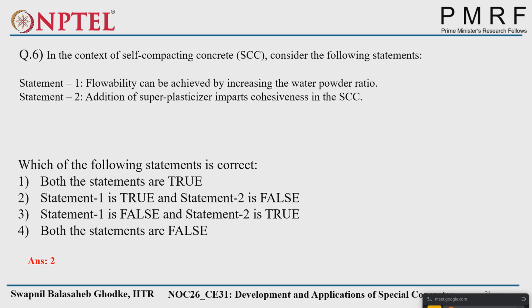Flowability can be achieved by increasing the water to powder ratio. Water increasing with powder kept constant, or water constant with powder decreasing, so automatically flowability will increase. And addition of superplasticizer increases the flow; it does not improve cohesiveness. For cohesiveness, a viscosity modifying agent is used, or otherwise you can improve the fineness content. These two you can do for increasing the cohesiveness. That's why statement 2 is false and statement 1 is correct. Understood? Any doubt? Okay, no doubt.